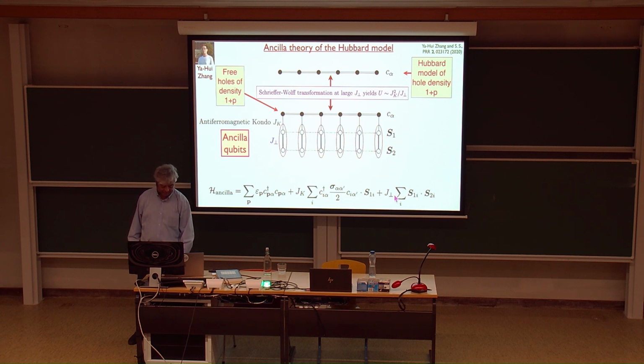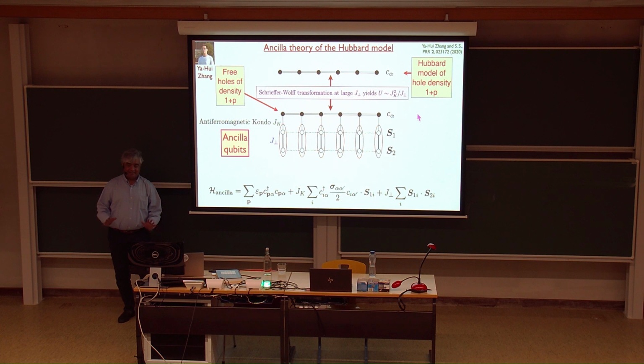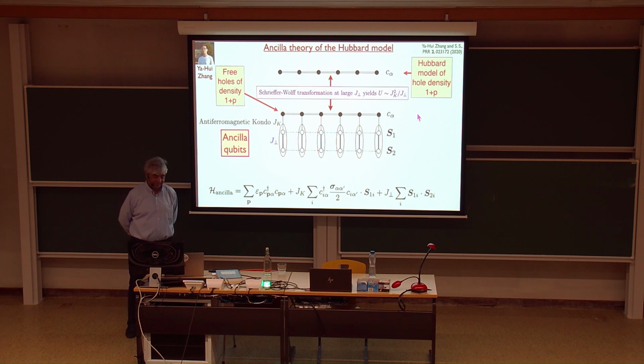Now, when J perp is large, you can do a Schrieffer-Wolff transformation. You can eliminate the triplet excitations from here, which is the same as integrating out the phi, and you get back a Hubbard model with U of order this number. I'm just rewriting the Hubbard model as a 3-layer model by this inverse Schrieffer-Wolff transformation. Everyone, this is a proven statement at this point, at least for large J perp. It has to be bigger than everything else, JK and T and even U.